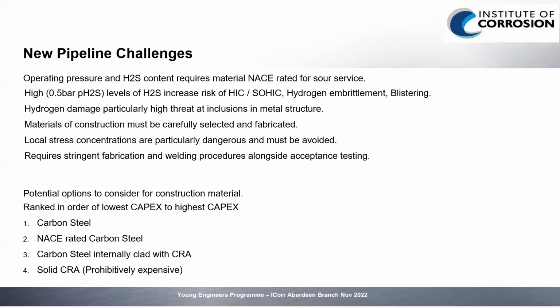At the bottom there, I have a list from cheapest to most expensive. We're planning to go down a chemical injection route to deal with the internal side. So we think we could get away with a couple of options, but we would recommend going with a carbon steel, just so you've got that backup in protection. From an external point of view, challenges are quite similar to most pipelines. So we would just recommend a standard coating system backed up by sacrificial anodes spaced along the line. So we've got a bit of a backup there as well in case anything goes wrong with the coating.